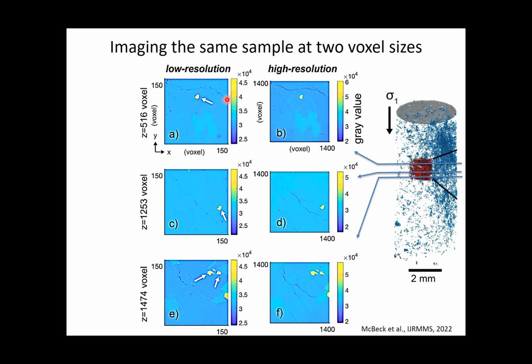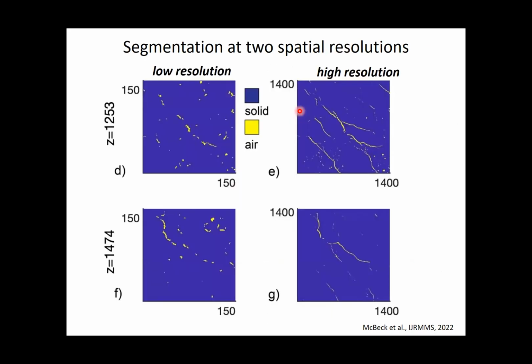And the question now is, if I extract the fracture here and there, which kind of error do we make? That's what we did. We took some of these slices. That's the low resolution. It's the high resolution. And the yellow spot is what is identified as a fracture or a pore. So at a higher resolution, we detect more, but still the main fracture here, we still detect it in the low resolution image.